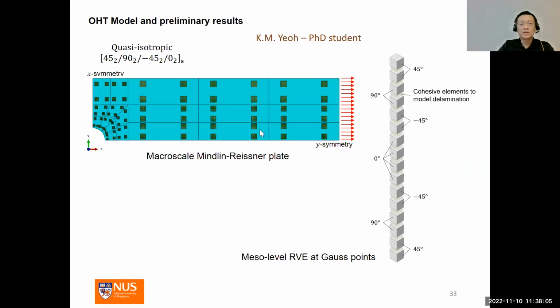Okay, so we have begun to model the damage in open hole tension. This is still very preliminary work, using a very coarse macroscale finite element mesh. In this case, we use a Mindlin plate, and in each of these plate elements, there are 4 Gauss points in which we place the RVE. The RVE is a stack of plies with cohesive elements inserted in between each of these plies, like so. The idea here is to see if this FE2 method can predict the delamination failure at the cohesive elements of the RVE at the Gauss points, or at least very close to the hole edge.